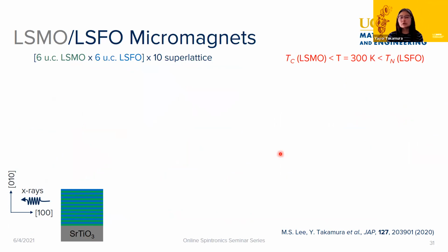So that was for a fairly thick antiferromagnetic layer. And what we also had was a sample where we grew a superlattice. So this is an LSMO LSFO superlattice. Individually, the layers were 6 unit cells in thickness. And what happened with the sample, which is maybe a little unexpected, is that the Néel temperature was fairly high, still above room temperature, but the Curie temperature dropped quite a bit, which meant that at room temperature we only had an antiferromagnetic layer. So basically we're only looking at ultra thin antiferromagnetic material. Even at 6 unit cells, this material was still antiferromagnetic.